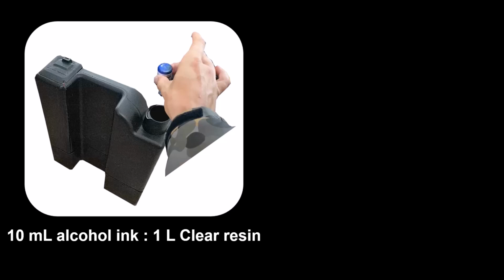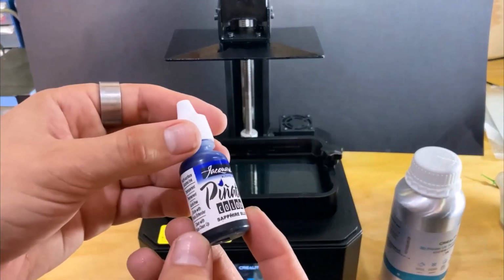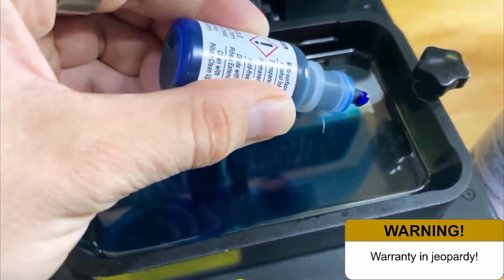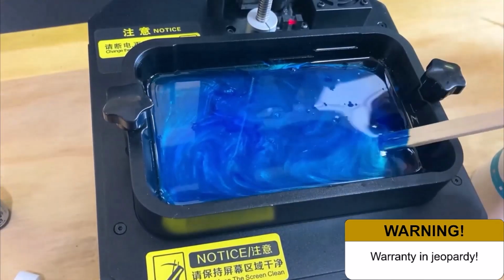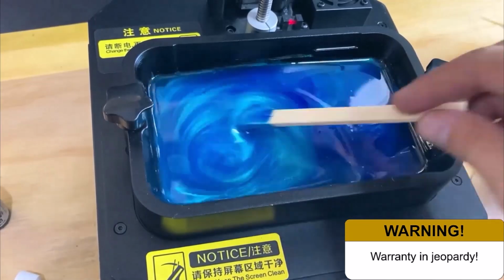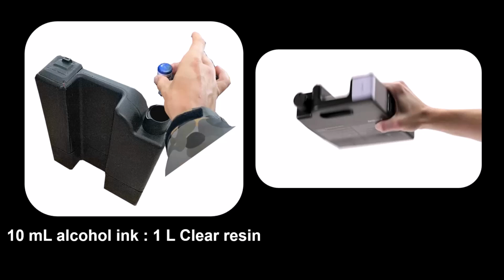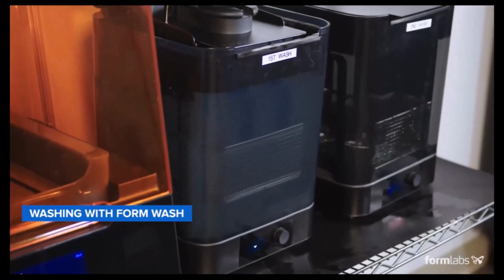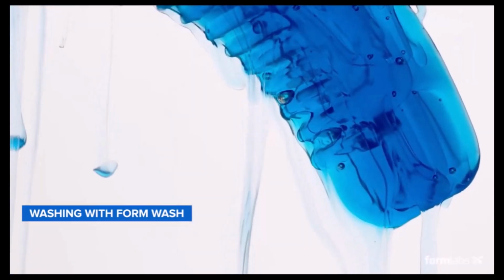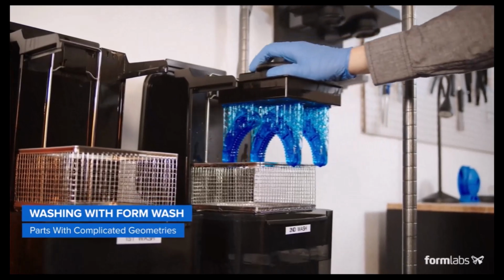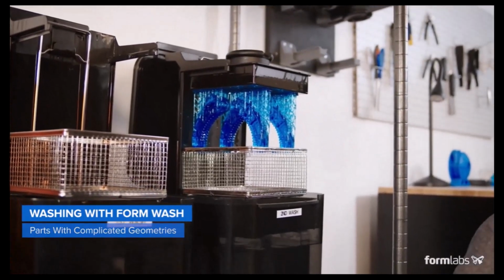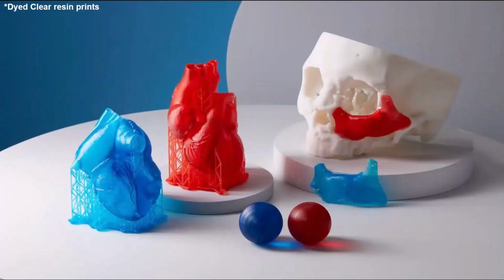We use clear specifically because dyeing it does not impact print quality on the same level as other resins. Bear in mind, though, that adding any form of substance to resin may increase the chance of print failures and will void the warranty of the printer should an issue arise. Once you've added the dye to the resin, shake the cartridge thoroughly and then resume the normal printing, washing, and curing process for clear. Note that the wash solvent will become dyed, so you may consider using a separate wash, either a wash station or a wash bucket, to avoid unintentionally dyeing other prints. And here's the finished product. I think that blue dyed print looks pretty sweet.